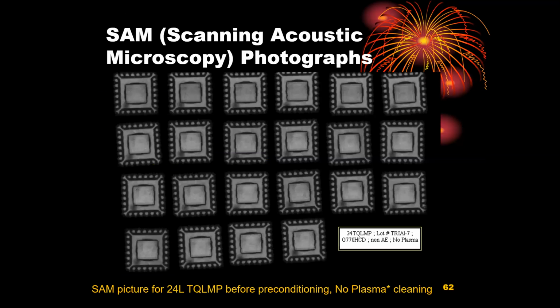We also did what is called the scanning acoustic microscopy at about 50 or 100 megahertz, considering the dimensions and the sound frequencies and attenuation patterns that were involved with the velocity, frequency, and the wavelength of the sound. So we did a 50 megahertz to 100 megahertz choice. And we could do the scanning acoustic microscopy with plasma cleaning or without plasma cleaning.